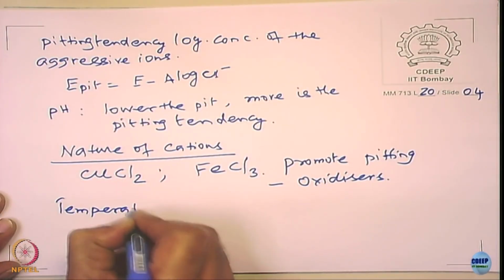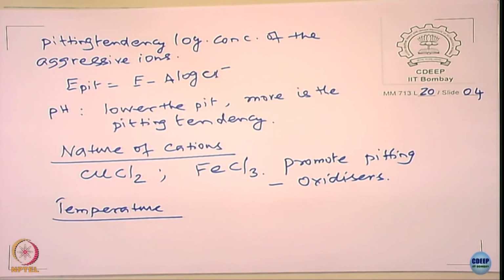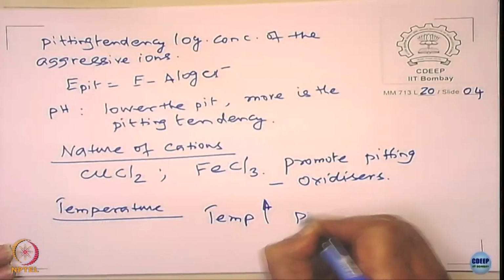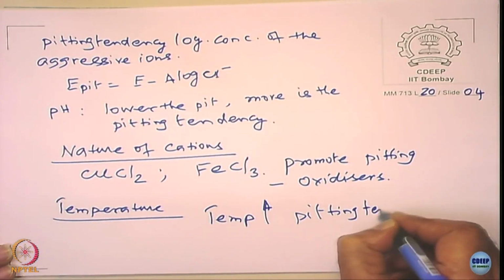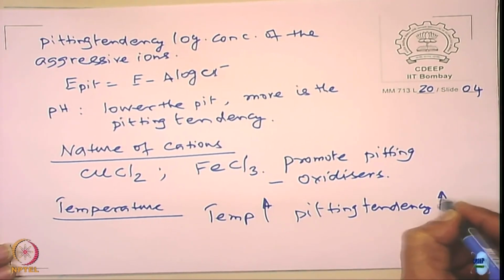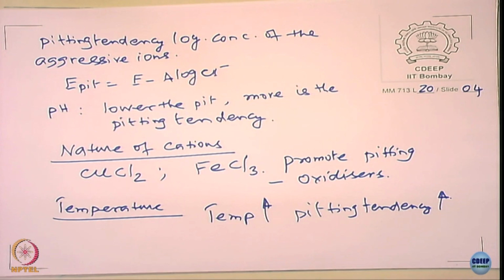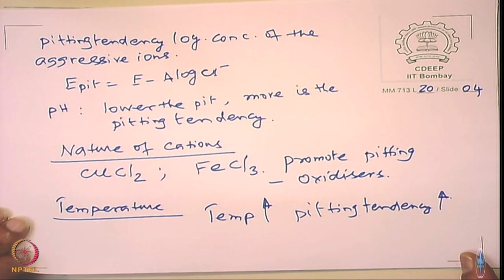So, what about the temperatures? What do you think will happen to pitting corrosion when the temperature increases? Diffusion will become faster, what more can happen actually? That is only one aspect of it. What also happens to the dissolution of the metal ion at the pit? Increase, right? So, when the temperature is increased, pitting tendency also increases. In fact, they also make some of the salts, formation of salts, and then it stabilizes the lower pH and stabilizes the chlorides. So, rise in temperature is always detrimental towards pitting corrosion.